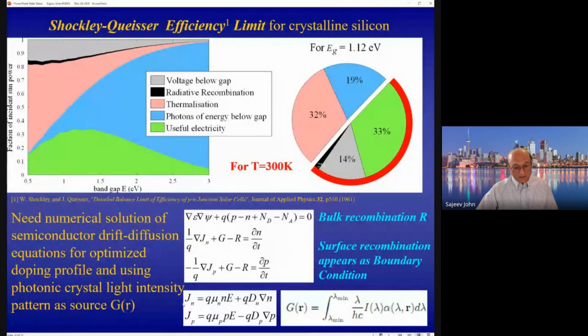And the last two equations are constitutive equations, saying that the current is being generated by the electric field generated by the gradient of the static electrostatic potential, and the gradient of the carrier concentration, which is this gradient of N, or the gradient of P. And there's a diffusion coefficient for the charge carriers and a mobility of the charge carriers given by D and mu. So then we have to solve this coupled nonlinear set of equations together with the Maxwell equations for the generation rate to actually find the efficiency of the cell.